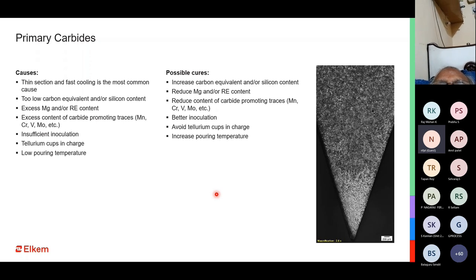Please make sure and ensure that these small parts of metal, which are about 250 to 300 grams, do not go back into your furnace, because they are a very strong source of tellurium, which is again a very strong source of carbides.